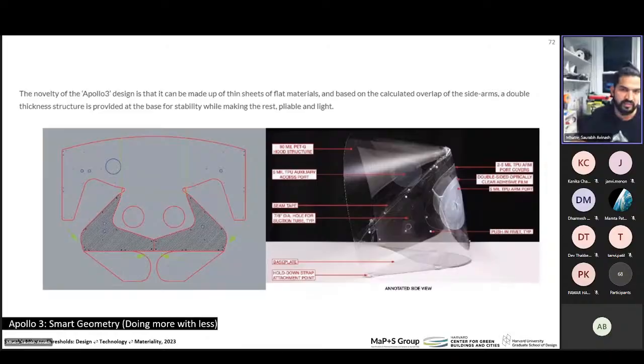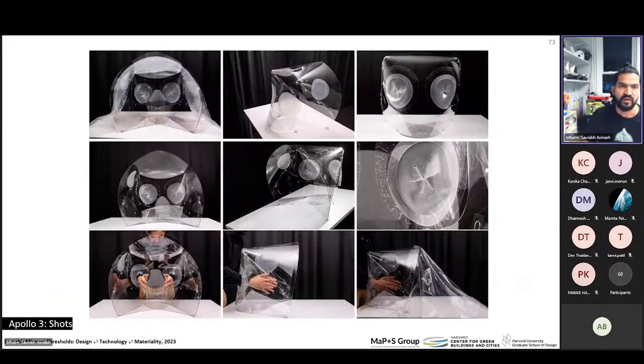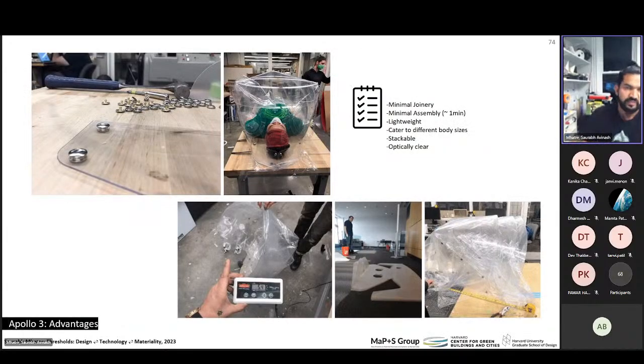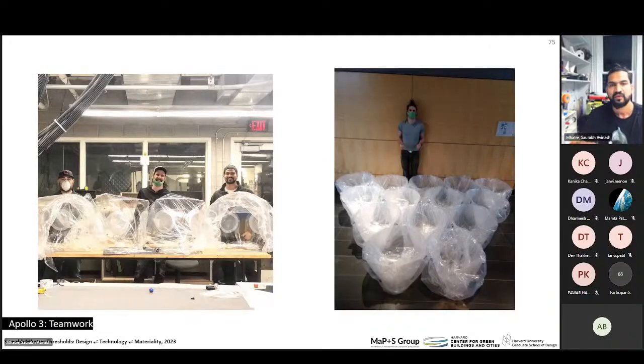We were able to use a thinner material in the Apollo 3, and by some overlapping of the geometry, we give a double thickness layered wall where the most strength was needed, which was at the back. Here are some detailed shots of the hood. The Apollo 3 was made up of a flat sheet, easy to manufacture, had minimal joinery and assembly, was lightweight, was compliant to cater to various body types, optically clear and stackable. We made 3 final prototypes in-house for the start and 20 more later after approvals and sent them to Mass General Hospital, MGH. And 50 more were manufactured after by a teammate who formed a company for the same.